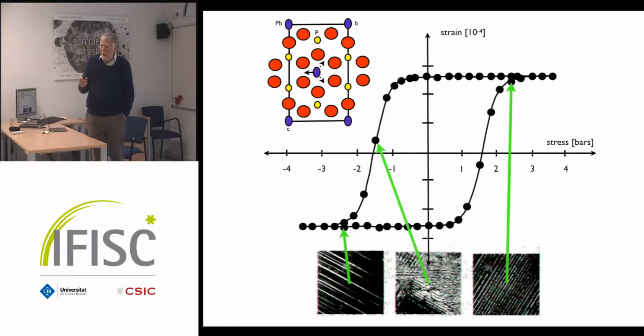Now the switching, atomistically, is just a little bit more than the thermal amplitude, right? So you're talking about a fraction of an angstrom. I mean, normally 0.02, 0.03, 0.04 angstrom. Very, very small. Macroscopically, on the other hand, this adds up. You have many atoms, right? You have really quite a massive deformation, and the strain here, as you can see, is in the order of